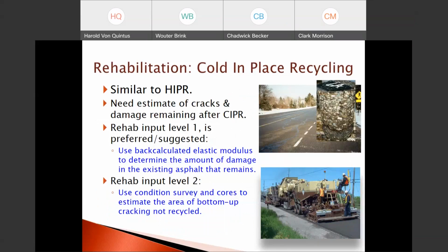And this is similar to hot in place recycled. We need to estimate cracks and damage remaining below our cold in place recycling layer, assuming we're not doing cold in place recycling of the entire asphalt layer. It's only a portion of the asphalt layer that exists. And we have rehab input level 1, which is preferred or suggested, and rehab input level 2. Rehab input level 1, just like our previous example, is going to use back calculated elastic moduli to determine amount of damage in the existing asphalt layer that remains.